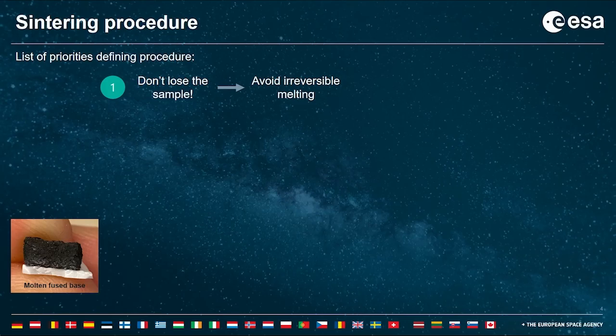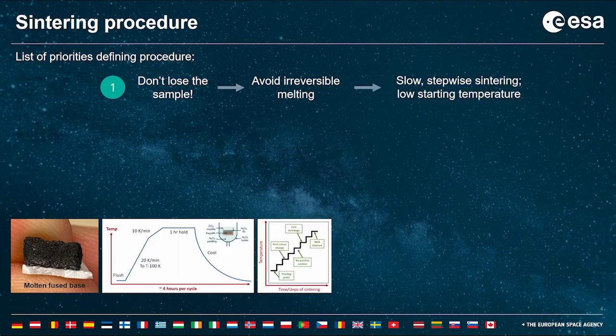So quickly touching on the procedure, there was a list of priorities that defined our procedure. The first one being, don't lose the sample. And that meant that we really wanted to avoid melting the material to the oxide crucible, because once it's melted, it's fused forever. So this meant that we did a very slow, stepwise sintering using a normal furnace. And after every heating cycle, we held for 1 hour. We then analyzed the material and decided how much to increase by. So it's a slow process, and we started at a safe temperature.